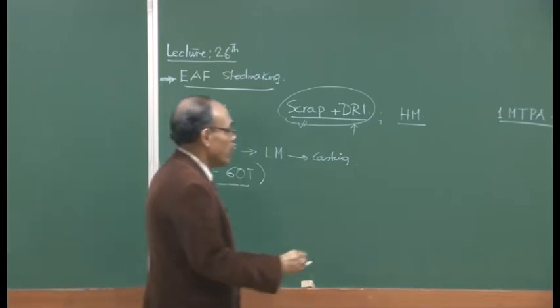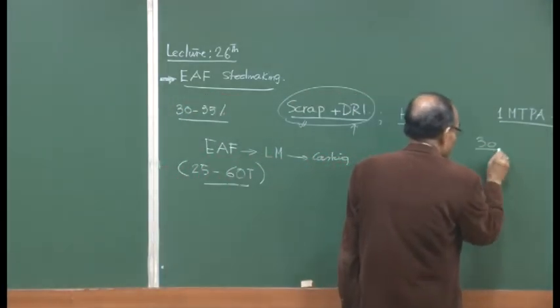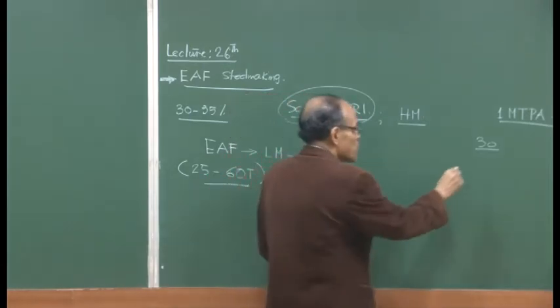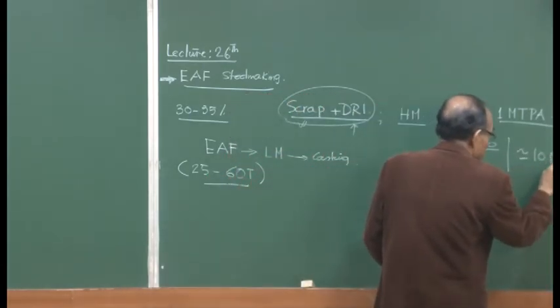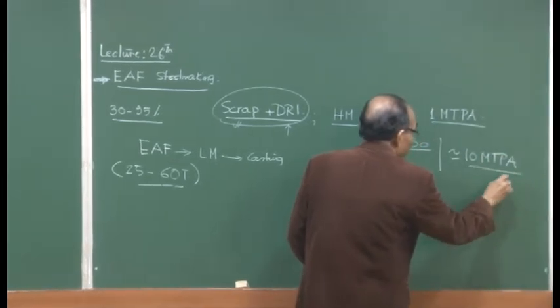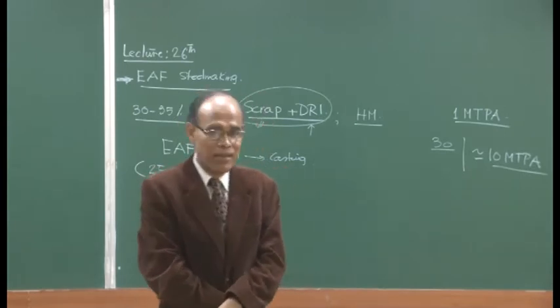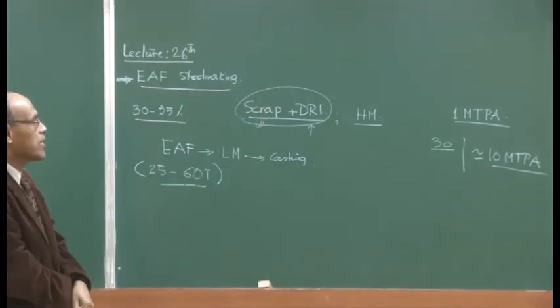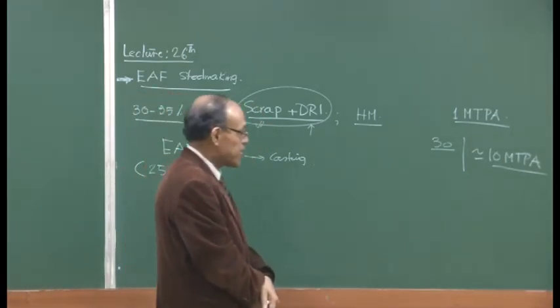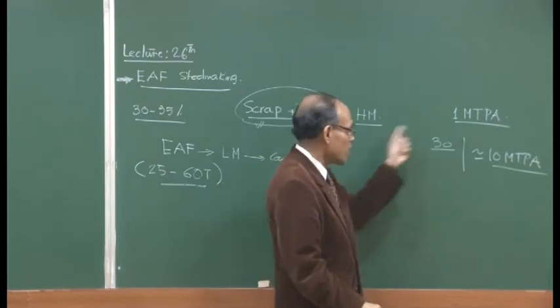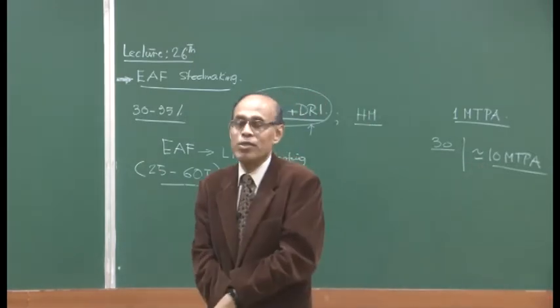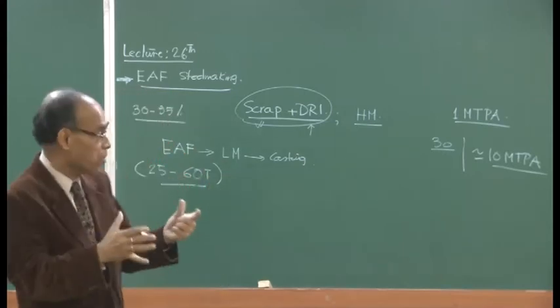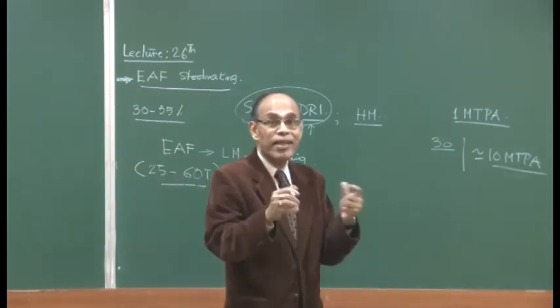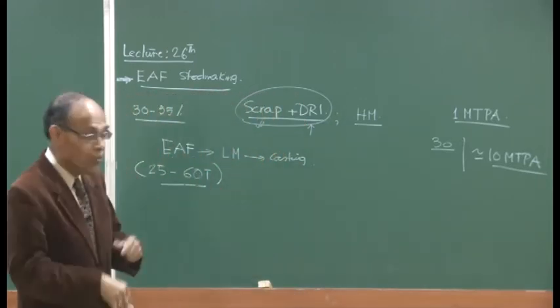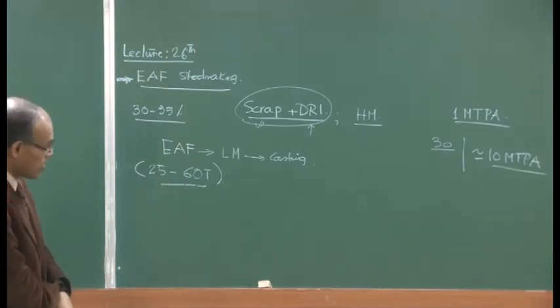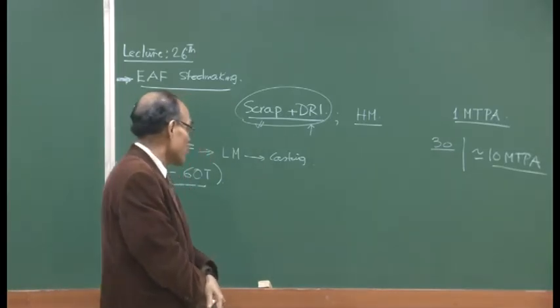Okay? So, we have at least 30 such plants in India to the best of my knowledge, and these collectively produce about 10 million tons per annum of secondary steel in India. Okay? So, a good chunk of Indian steel comes from integrated steel mills, from the secondary sector or the arc furnace sector, about 10 million tons, and the balance, which constitutes our current production rate of 110 million tons, comes from induction furnace steel making, which is a very peculiar scenario, and I am going to address this perhaps in the last lecture when I talk a little about the steel making scenario in the country.